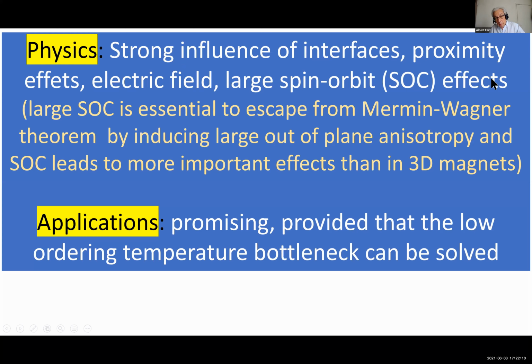Also, the spin orbit effects are more important than in 3D materials. Why? Because large spin orbit coupling is essential to escape from the Mermin-Wagner theorem. We say that for isotropic spins, there is no possibility of ordering except at zero temperature. But this is because there is some divergence of the excitation of magnons. But you can escape from this theorem with some large anisotropic field, large out-of-plane field, for example. And in fact, this anisotropy can be induced by spin orbit effects.